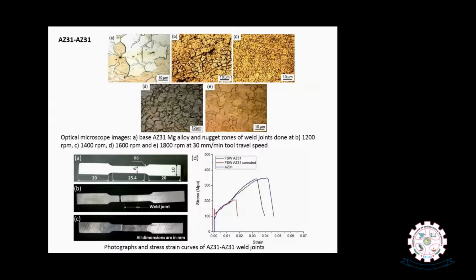The weld joints were exposed to a corroding environment and subjected to corrosion, and then tensile samples were prepared from those samples, and we investigated the effect of the corroding environment on the mechanical failure also. The friction stir welded joint has shown better strength compared with the base material because of the smaller grains which we achieved in the weld joint in the solid state itself.